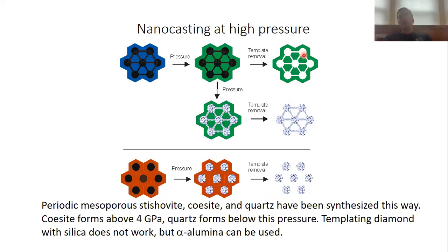If you choose high pressure conditions, you can do this, because high pressure greatly facilitates crystallization, and that is basically for two reasons. So first of all, there's a kinetic reason. You can activate bonds using pressure. So when you apply pressure to a material, then you apply mechanical stress to the bonds, so the bonds break more easily and also reform more easily. So this way you can actually overcome activation barriers of reconstructive bond formation. And secondly, there is a thermodynamic reason for this.